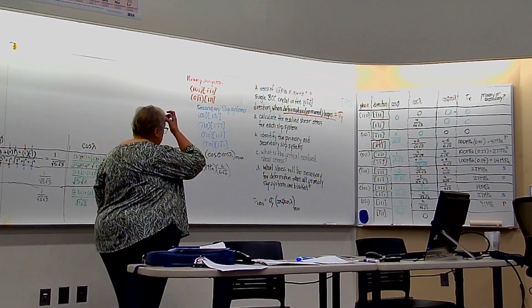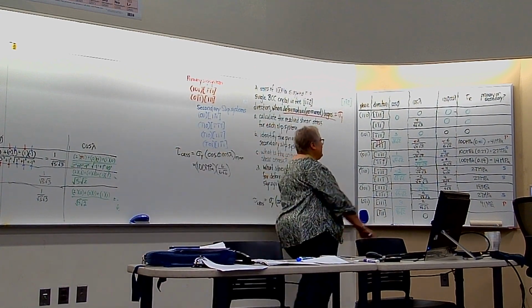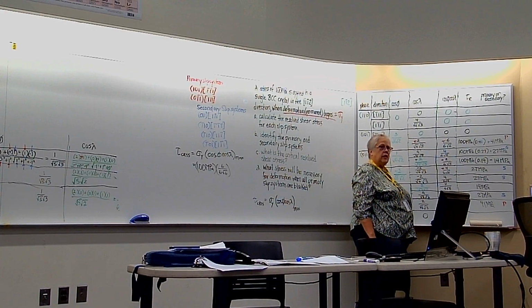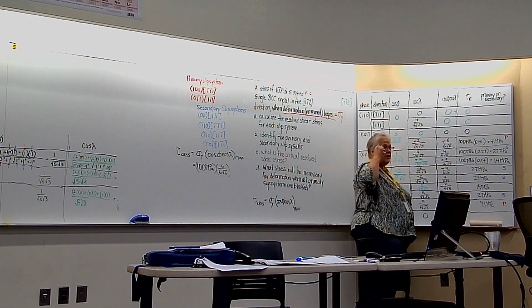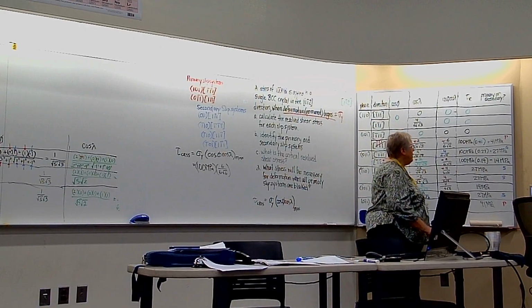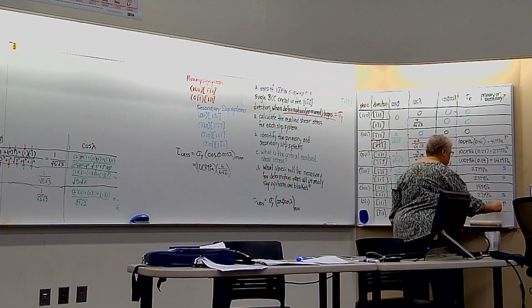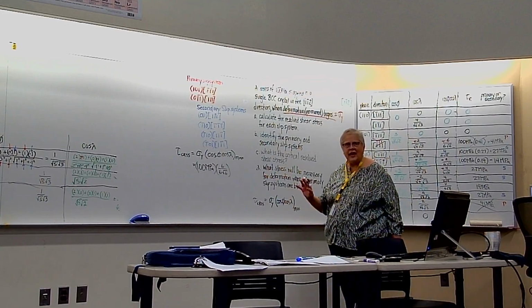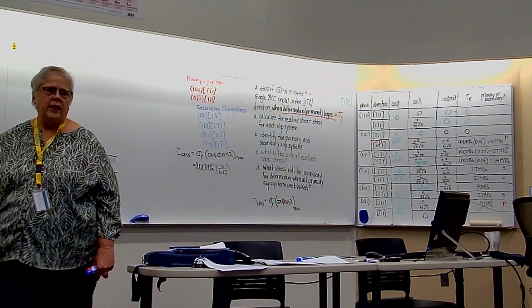Now, what that means is, when any slip system gets to 41 megapascals, it will be activated. When any of these get to 41 megapascals, it's activated. When the primary slip systems are blocked, then the secondary slip systems have to reach a resolved shear stress of 41 megapascals.